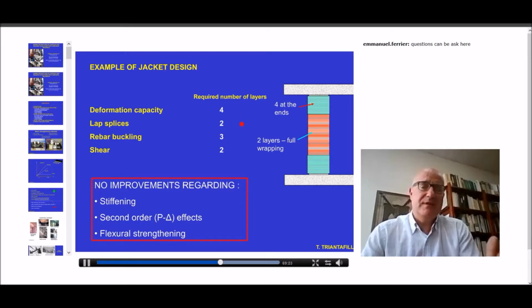Let's assume that using the models that we discussed already, we have calculated that we need, for example, 4 layers to increase the deformation capacity, the ductility. We need 2 layers to prevent lap splice failures, 3 to delay rebar buckling, and 2 layers to prevent shear failures. In this case, we apply 2 layers all along the height, all along the length of the column, and we add 2 more at the ends, so that we have a total of 4, and by doing so, we satisfy all requirements at the same time, the shear resistance as well as all the other failure modes.